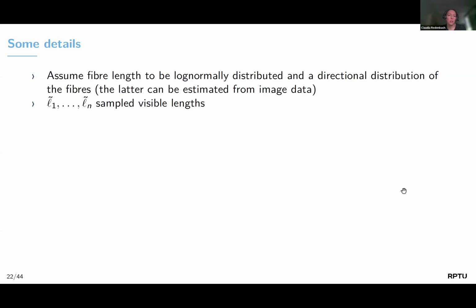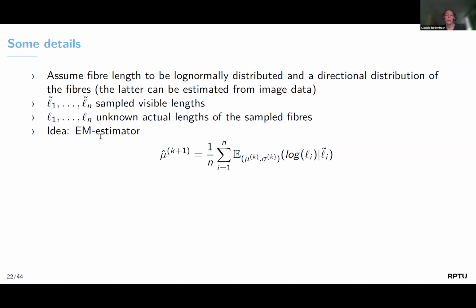What we could do now is assume we have a single fiber segmentation. We would look at the visible length. So this is the length of the fibers that we see in the image. It's not the actual length that is denoted by L without the tilde. So for fibers that hit the edge of the window, it would mean L tilde we see, and L is what is in the window plus what is outside the window.